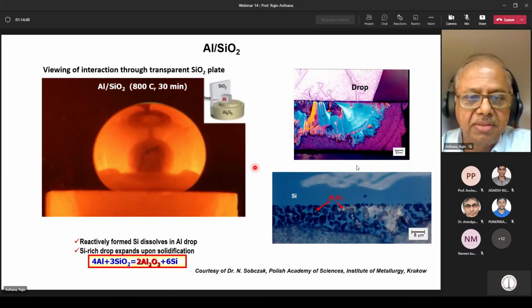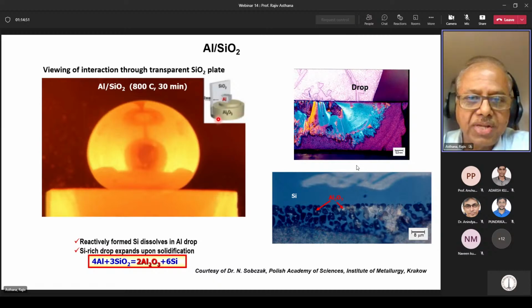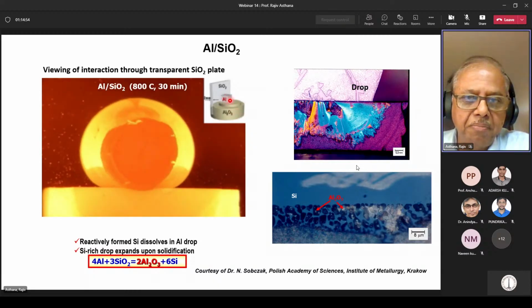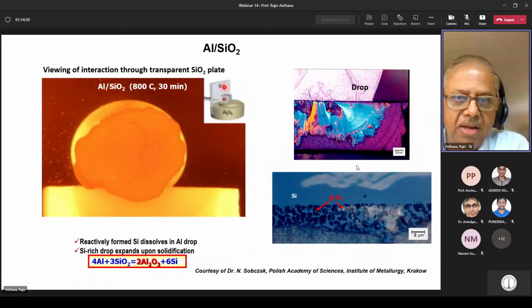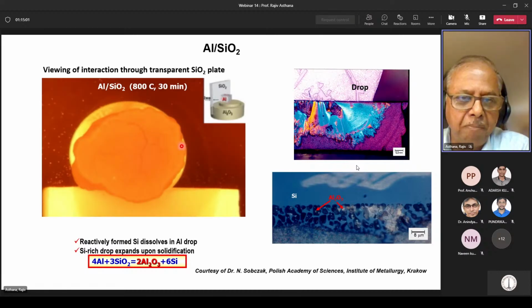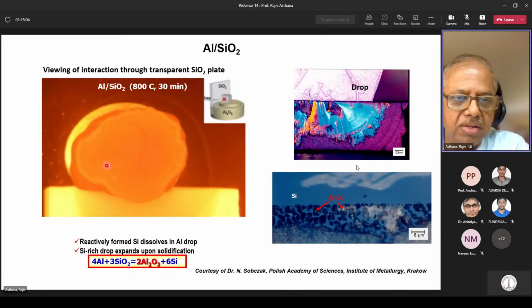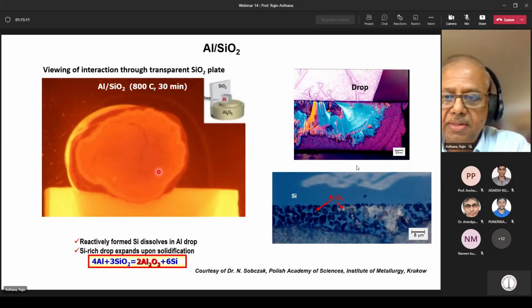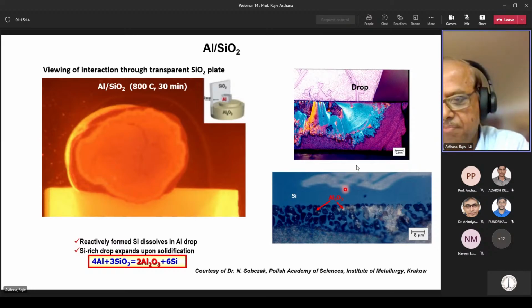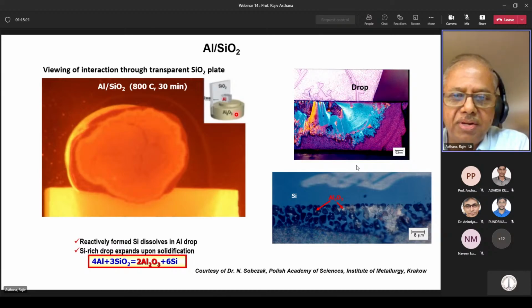Here we are looking at this kind of a system. You have aluminum oxide on which you had a solid piece of aluminum, and this is the quartz, transparent silica plate. So inside the vacuum system, when you melt aluminum, you can actually see through the silica quartz how the liquid is spreading and how the reaction layer is forming. And then later you can do chemical analysis and microscopy to see what phase is formed. But this kind of real-time visualization is interesting because these quartz plates of silica allow you to see through the region and study the reactions between aluminum and silica.